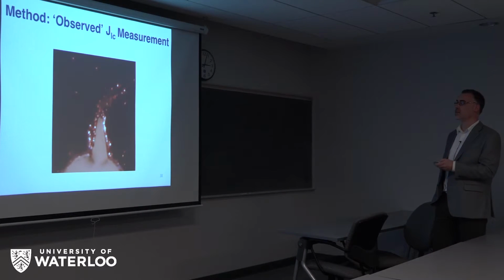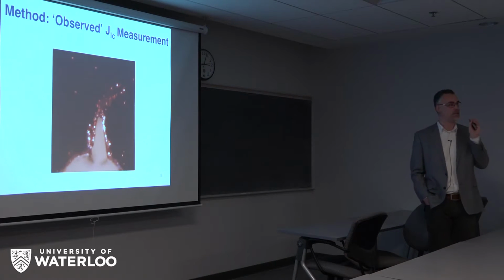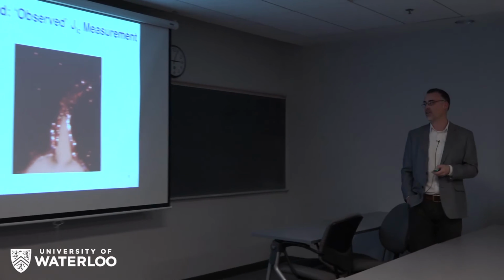And then we also did it optically by trying to capture the instant when we could see crack growth. And that was actually quite challenging, because here's no crack growth, and here's crack growth. And it's this tiny little white line here. So it was very difficult. High resolution, but still very difficult to see.